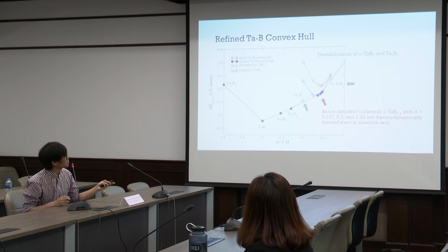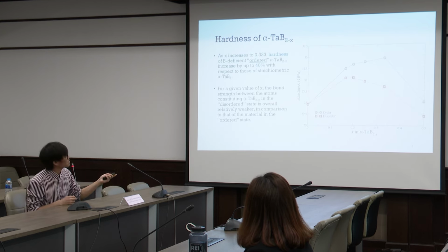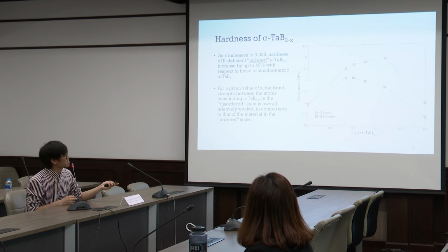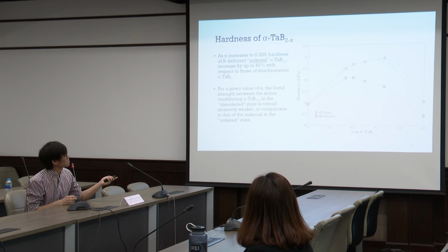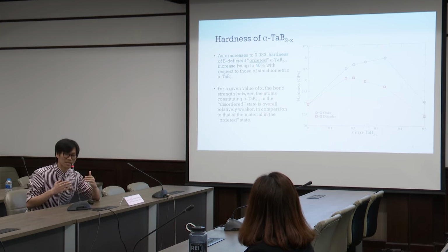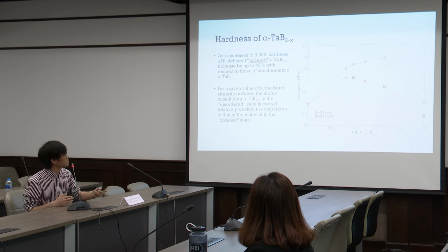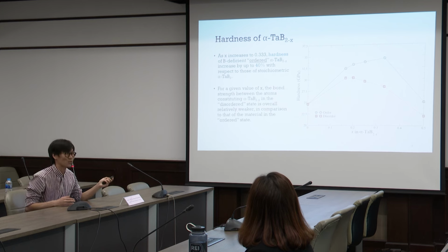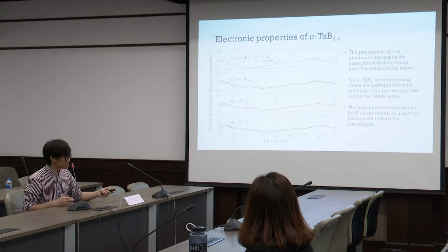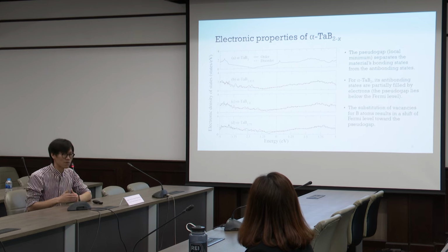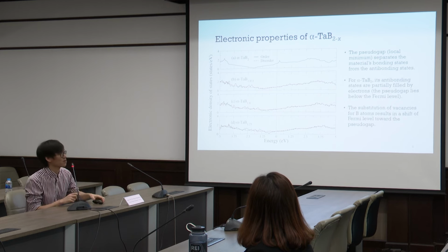Another thing that is very interesting is that when there is boron vacancy in this alpha phase TaB2, we observe a significant enhancement of the mechanical performance in this material system. For instance, here, where x is about 0.3, this is the concentration of vacancy in the system, the hardness of this alpha phase TaB2 can increase about 40% as compared to the stoichiometric one. We also try to provide the physical reason behind this improvement in the stability and the mechanical performance of this TaB2 compound.